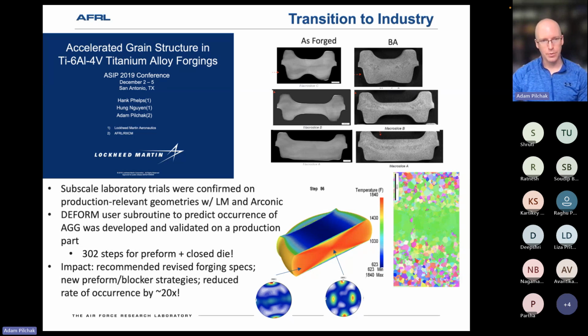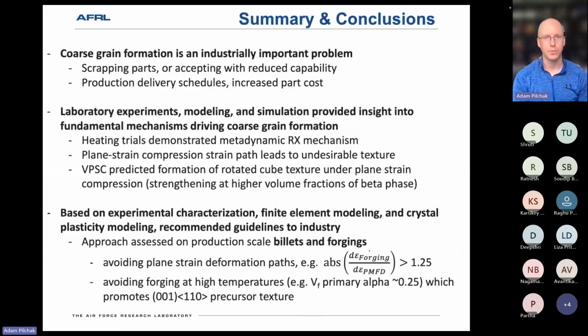So in addition to that subroutine, we also came up with rules of thumb, like, try to avoid plane strain compression, and if you're going to do that, don't put in strains greater than 1, which led to some revised strategies for some of those early forging operations. You call them either preforming or blocking. And at the time, within a couple of years, we'd reduced the rate of occurrence of this by roughly 20x.